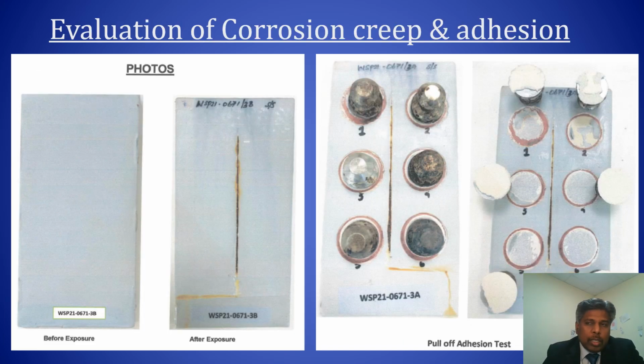The photos that you see here are the results of the testing that was done for C5 high durability as per ISO 12944 part 6. On the left side, what you see is the measurement of creep from the scribe that was put in, and you hardly see any increase in the width of the scribe. That is, there's no creep. On the right side, we see the pull-off test and the results that we got after the neutral salt spray exposure, 1440 hours exposure. So you've got very good results of the complete system from the testing, again from a corrosion protection perspective.